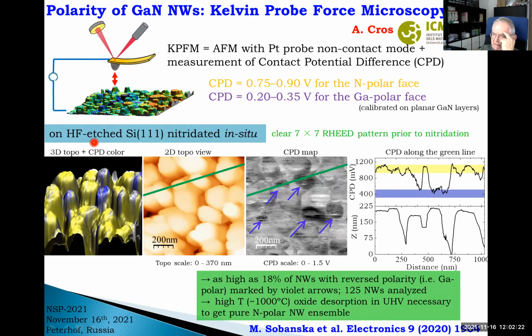In this particular case, the silicon substrate was prepared by the so-called HF dip. This is a very popular procedure, because the only thing you need to do is put your wafer in the diluted HF for a minute, then you take it out, dry it and transfer it in air to the machine. And the protection mechanism is such that it's well known that during such a procedure, the surface is coated with a hydrogen film that is supposed to protect the surface against oxidation during the transfer to the vacuum system. So this is how we prepared our substrate. We saw a very clear 7x7 RHEED pattern prior to growth. So we expected, okay, we have a clean surface.